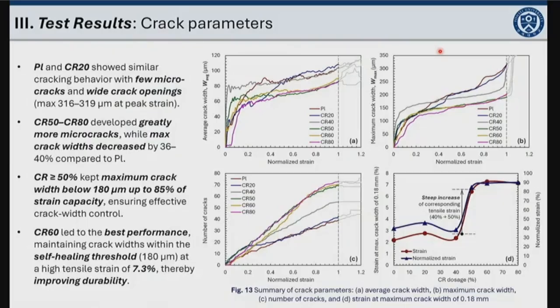The plain and CR20 sample show the fewest microcracks and the widest crack openings, over 300 micrometers, at the peak strength. However, by incorporating the crumb rubber more than 50% here, the cracking behavior was significantly improved with smaller crack width and higher number of microcracks.